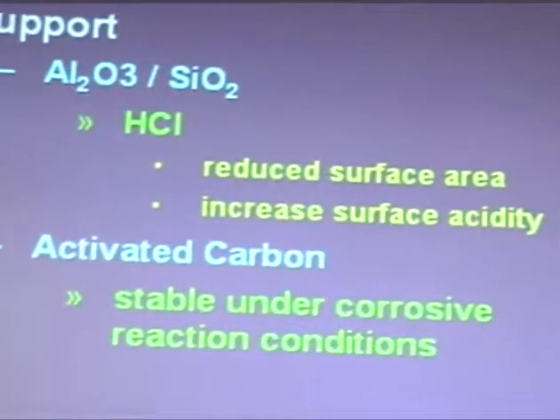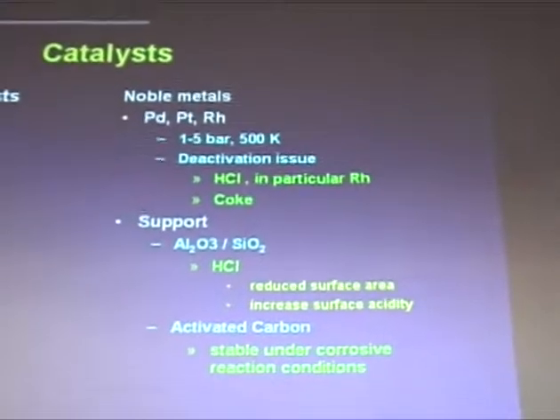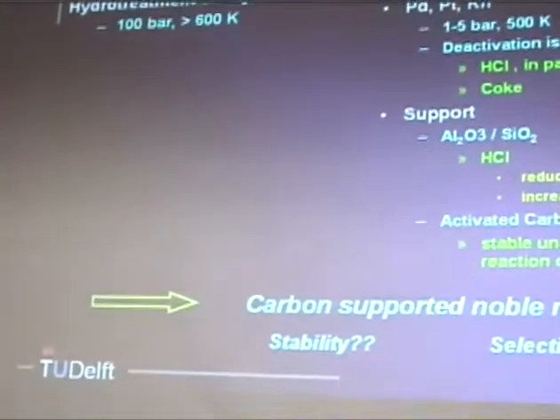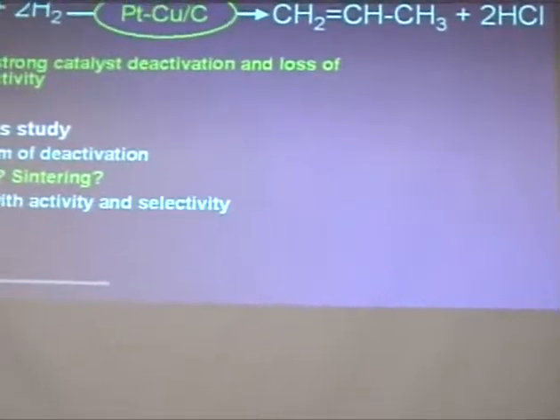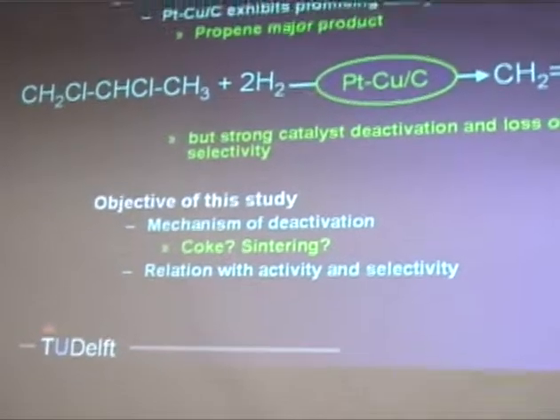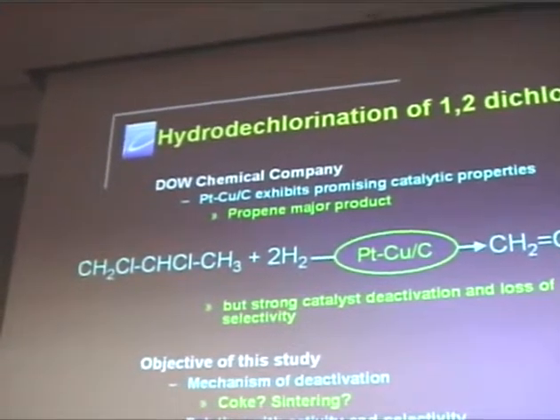Supports, you can choose between ceramic supports. Alumina, silica are used, as well as activated carbon. Alumina, silica, of course, in this acid atmosphere will become more acid, of course. And that means that you could have some reorganization of the surface and also more coke formation. Activated carbon is stable, so in a way that's the obvious choice. And then the point still is stability and selectivity. And then to the project I'm talking about, Dow Chemical Company has published a paper